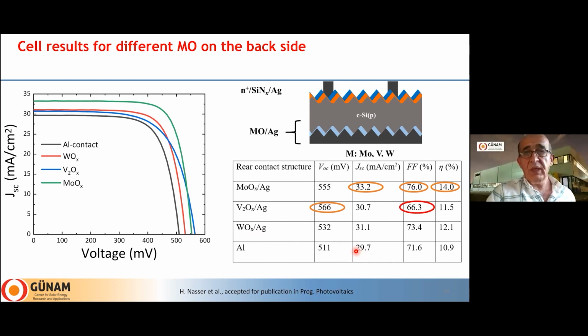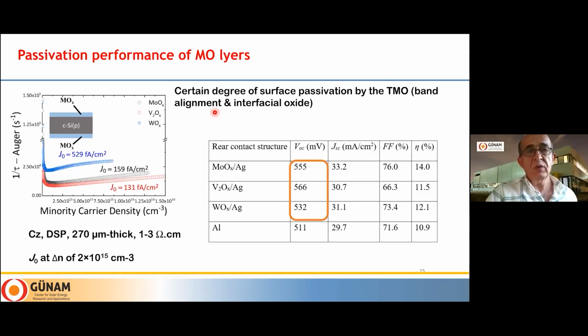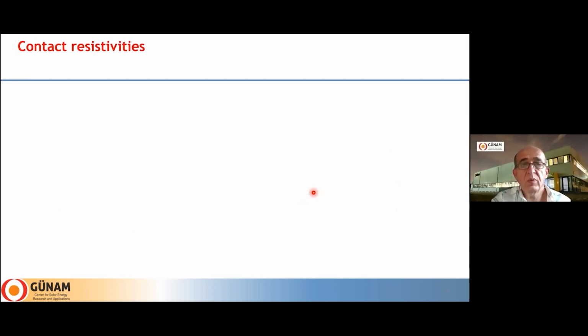Okay, now let me show some of the details. For instance, the passivation can be identified by measuring the lifetime from these structures, and we fabricated special samples to measure the lifetime in these structures and to understand the surface passivation quality. So the reverse saturation current is identified and measured, which directly gives us the open circuit voltage values. So as I mentioned already, vanadium oxide is the best in terms of the passivation quality. Okay, let me now move forward.